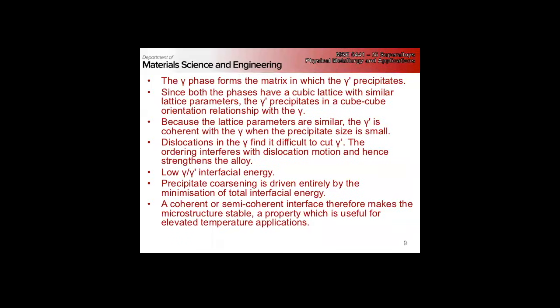100 parallel with 100, faces the 100 direction parallel with the 100 direction, right? So there's a perfect cubic lattice correspondence. The lattice parameters are very similar, so the gamma prime is coherent with gamma when the precipitate size is very small. And as I said before, dislocations in the gamma are difficult to cut into the gamma prime because the ordering interferes with the dislocation structure, right? Low interfacial energy, right?